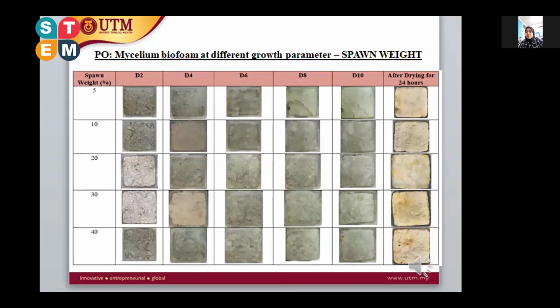Next. So this figure shows the appearance of a biofoam from PO at different spawn weights. We can see a different appearance of the mycelium biofoam at different spawn weights, which are 5, 10, 20, 30, and 40. And we can see that 40% spawn weight after drying for 24 hours shows a fully colonized mycelium.